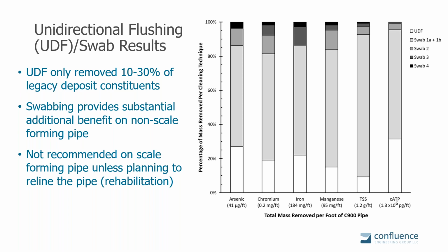If you're going to do swabbing or pigging on unlined cast iron pipe on a scale-forming pipe, you probably have to have a relining plan, a rehabilitation plan. So it's key to know, you might think you've gone out and you've cleaned your system ahead of a change because you flushed, but you've probably removed about 10% of the material. The rest is still there and able to react to the chemistry and hydraulic changes that are yet to come.